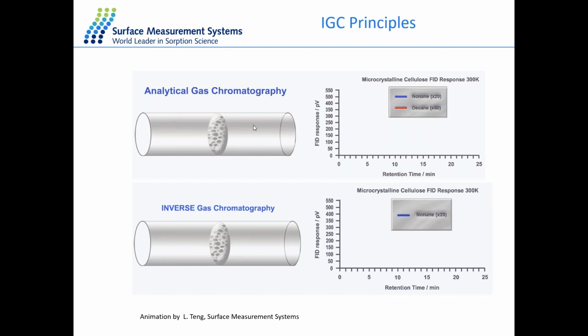So compared to analytical gas chromatography, what you usually have is a mixture of gas phase probe molecules, which you would inject into a column. And depending on the interaction with the column, you'll have a separation of these molecules. So in turn, what you would see is some peaks here based on the retention time, and you can go ahead and analyze these peaks. With inverse gas chromatography, you're actually packing the column with your sample of interest, and then we would inject known probe molecules, so a mixture of some alkanes and some polar molecules. And upon the interaction with your sample materials, you would obtain different retention times and different peaks, which you can go ahead and analyze and obtain some physicochemical properties from.